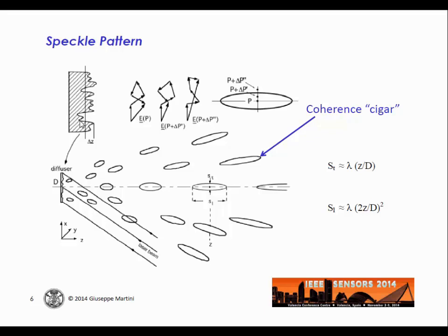It is a geometrical roughness with a correlation length in the target plane smaller than the wavelength of the light we are using, and it has a span along the line of sight of the interferometer higher than the wavelength.